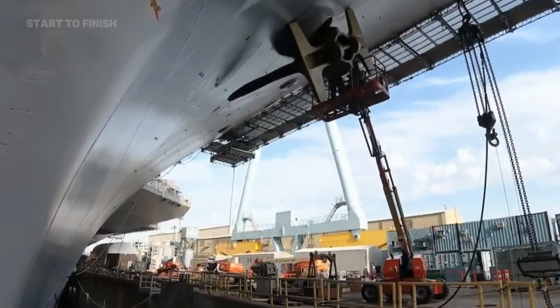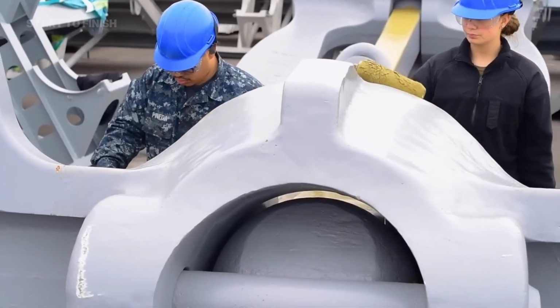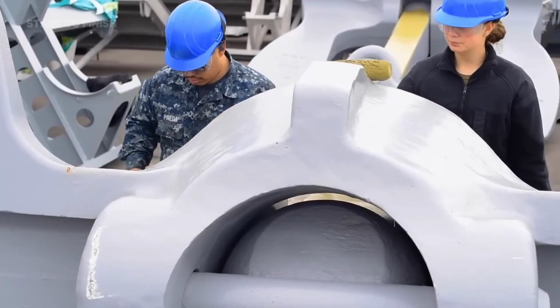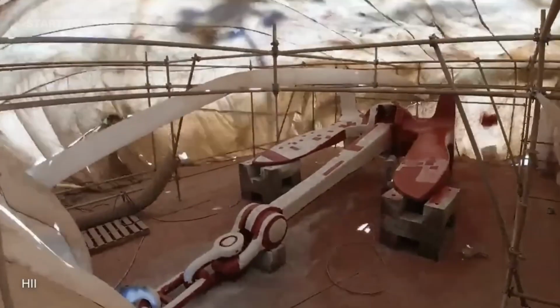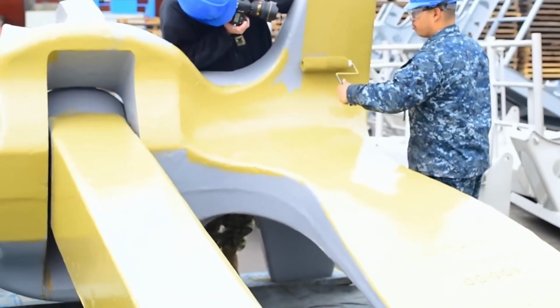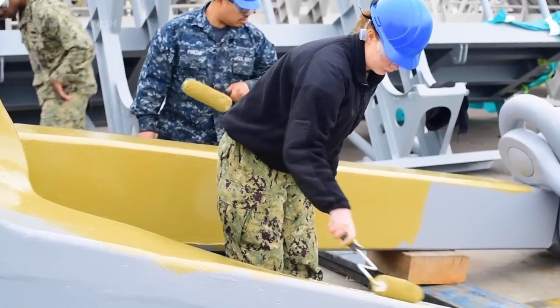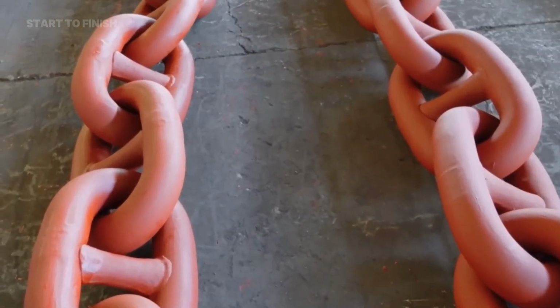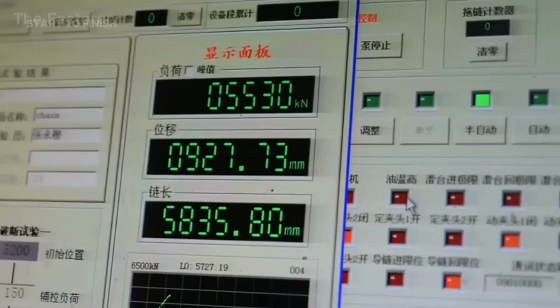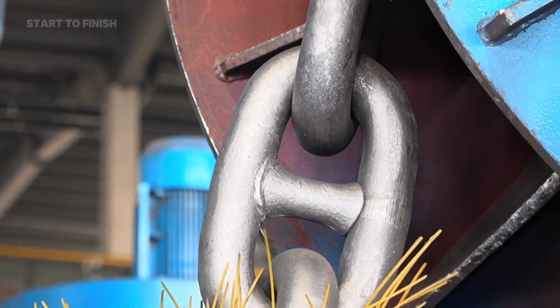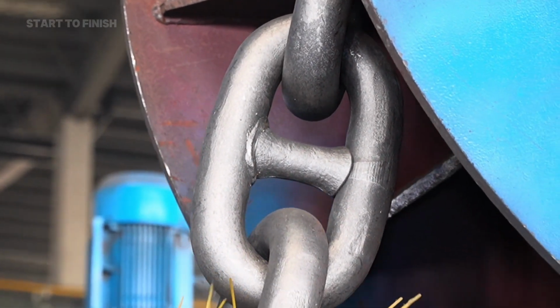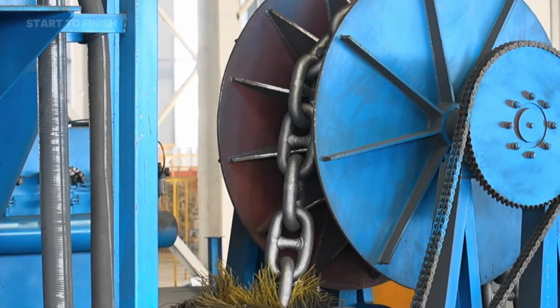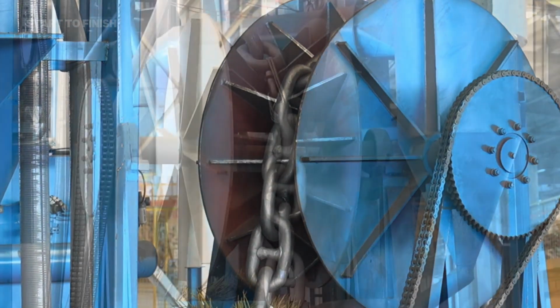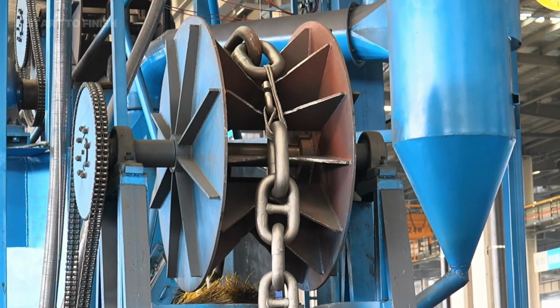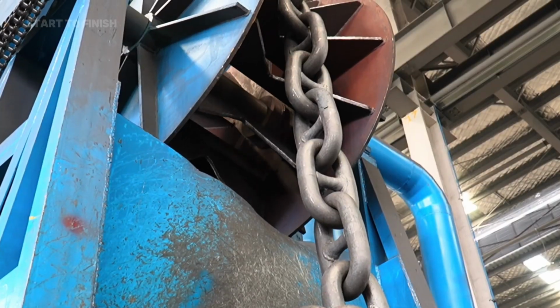For chains used in offshore rigs or military vessels, additional layers are applied. These include epoxy coatings, polyurethane paint, or even thermal spray aluminum, each designed for specific conditions like temperature variation or deep sea pressure. After coating, the chain passes through a curing chamber where controlled heat hardens the protective layer. Every section is visually inspected, weighed, and measured to verify coating thickness. Any inconsistency can lead to rejection. Once approved, the surface is polished and lubricated to ensure smooth operation through anchor handling equipment.